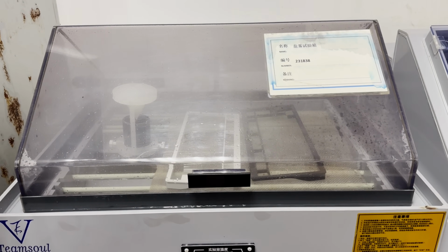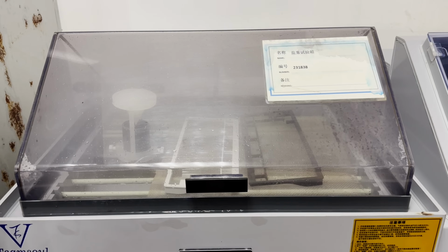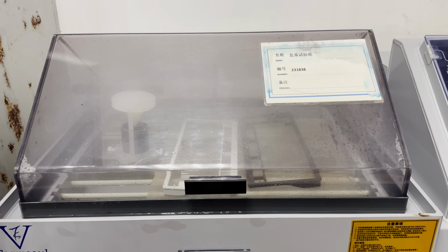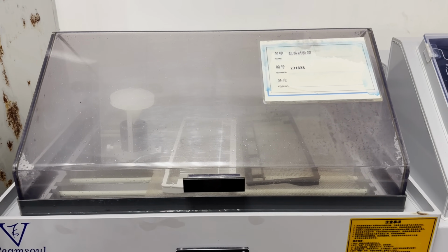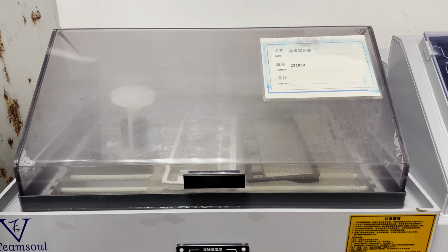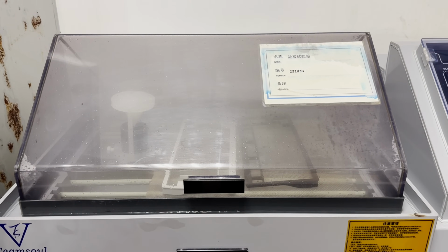And that is something that we specifically also did with the metal cases. That was for the raw case, one of the most important tests, because when we didn't coat the case, it would fail this test very, very fast. But by adding a UV coating on the outside, it would pass this test and it was good enough to go. But that's not all.